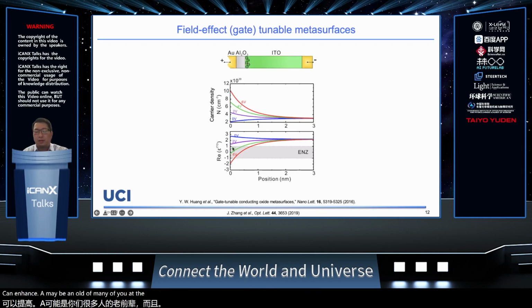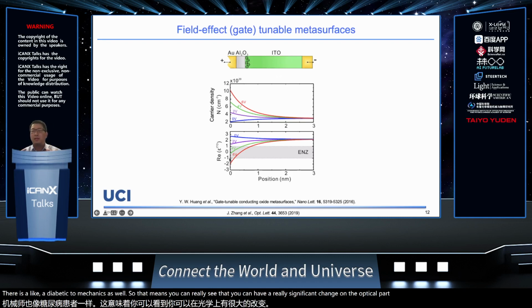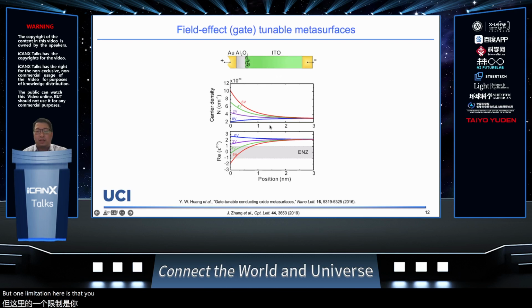At the same time, you can change the permittivity from positive to negative, which means from dielectric to metallic as well. So you can have a really significant change in the optical property by applying voltage here. But one limitation is the width here, which we call the Debye length. It's actually quite thin, only 1 or 2 nanometers. That means your active region is quite thin, 1 to 2 nanometers.